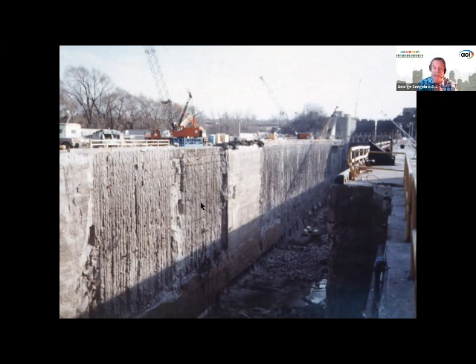But I put this shot up because the paper that I'm going to have you take a look at for protection during the winter has some interesting comments. These guys in Canada would set these forms. They're about 1 meter thick, new cladding, and as cold as it was, the forms were set up, and then heaters were blowing inside the forms to warm everything up prior to the pour. And we had to crawl inside too to look at the surface prep and everything. And it was more comfortable being inside the forms when the heaters were on than out in the middle of this cold gangway, surrounded by nothing but ice cold metal.